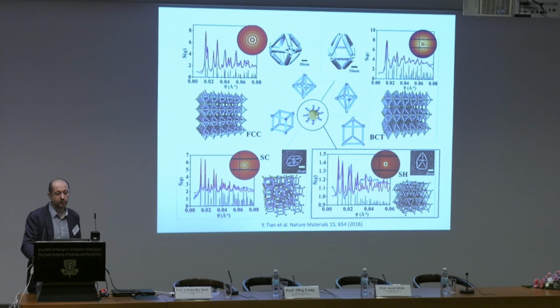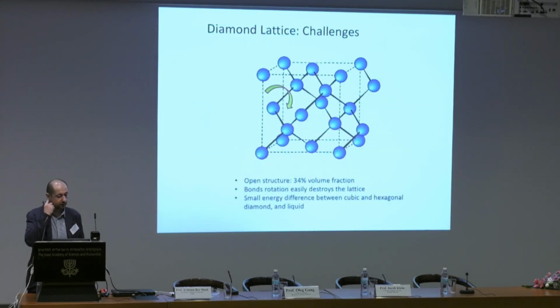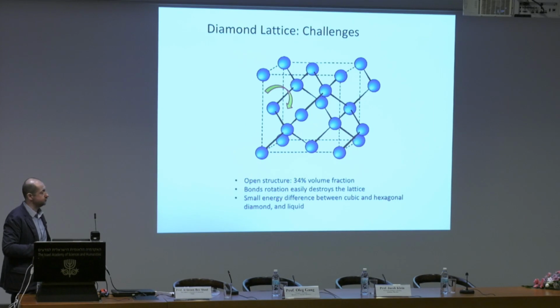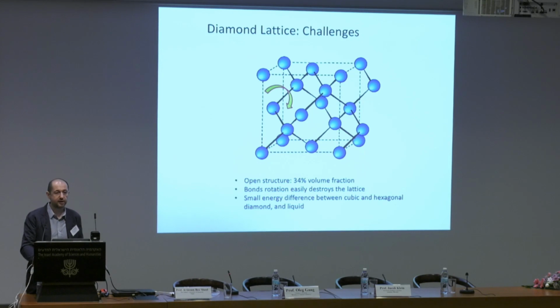So now, having this in mind, we wanted to address also a question which has been outstanding for 25 years or so in the field of self-assembly. It's the formation of the diamond lattice. The diamond lattice was first proposed in the late 80s because of the interest in photonic band gap materials for assembly of colloids, but then somehow it became one of those structures which seems to be easy, but in principle was very difficult to make. One of the reasons is that it's an open structure, 34% by volume, and it is very easy to destroy the lattice through rotations. There are several phases which have similar energy.